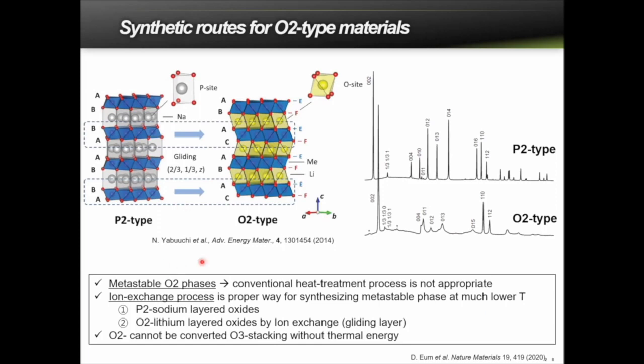It has been well known that this kind of O2 structure can be derived from the P2 type structure. And these P2 type structures are easily synthesizable at high temperature through sodium phase formation. So we prepared this sodium version of the lithium excess P2 layered structure, ion exchanged the sodium for lithium through a soft chemical method, and then attempted to obtain this O2 structure.